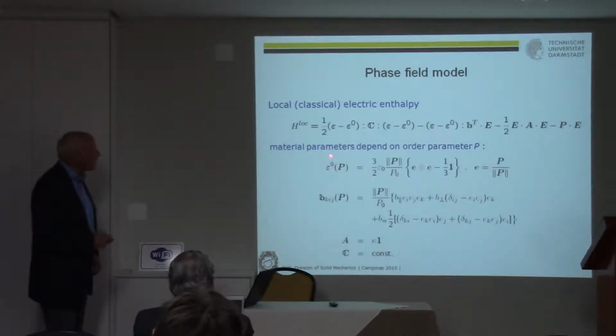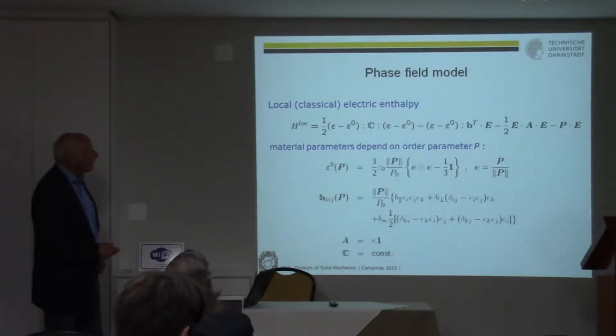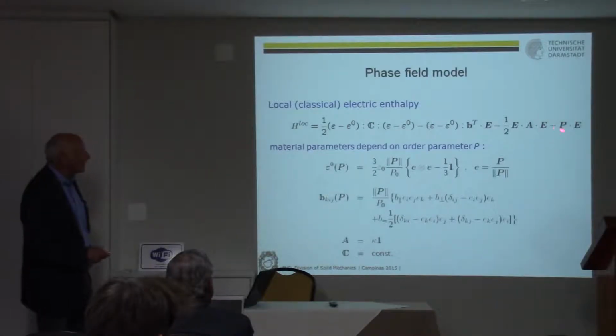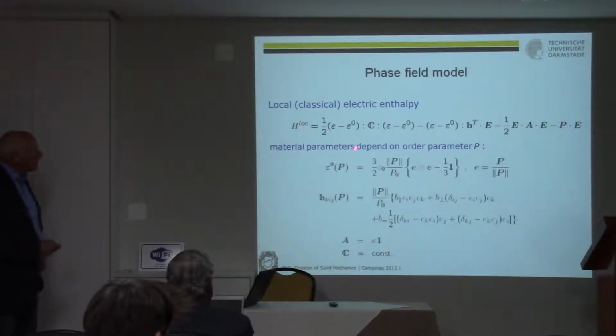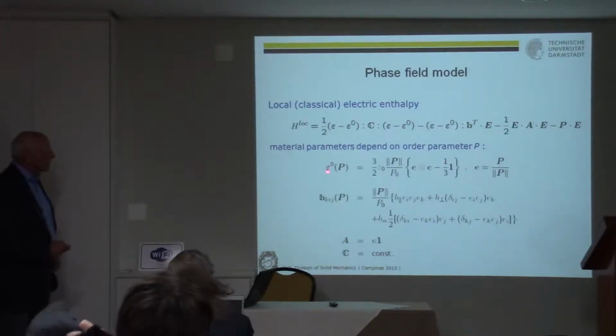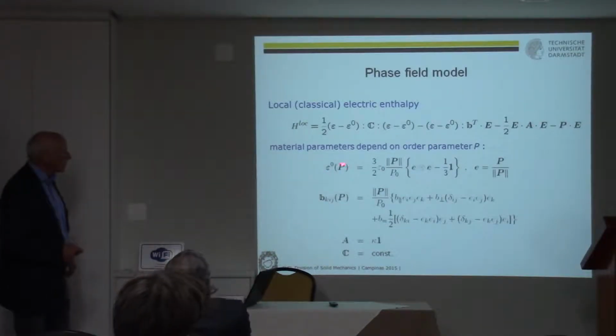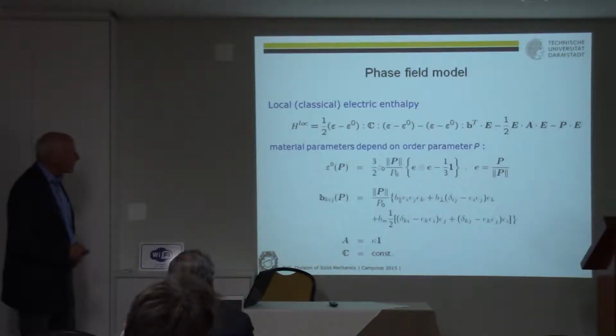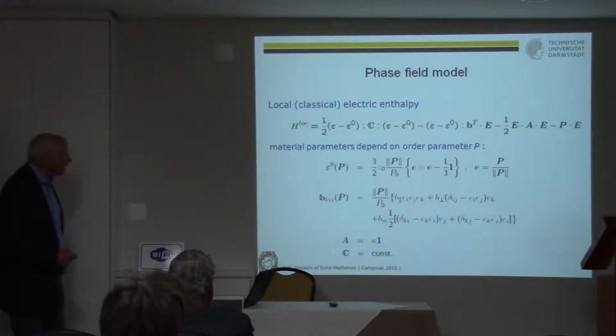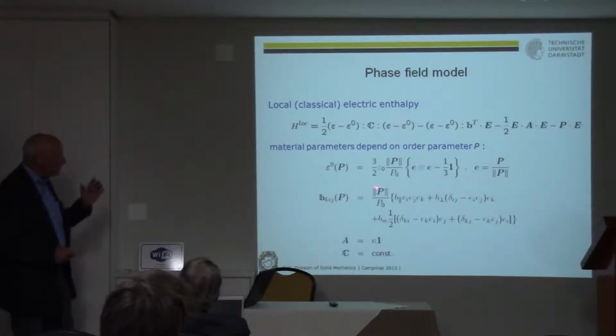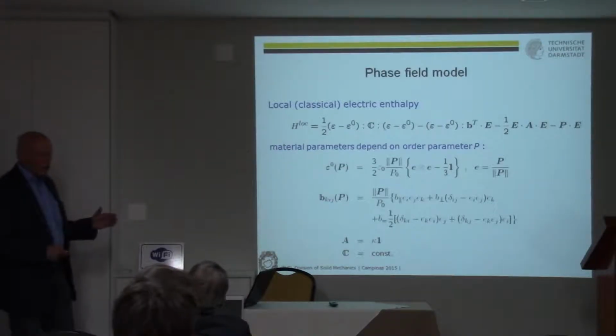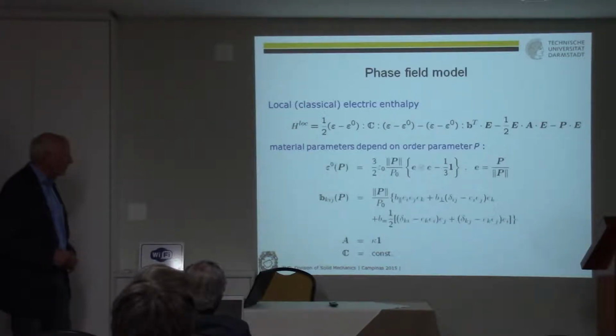Okay. Now the electric enthalpy consists of several parts. The first part is the pure mechanical part here, and then the pure electrical part here, and then the coupling, and then one term for the polarization, and epsilon naught here. This is given by the initial polarization P, as I mentioned, and here this tensor, b_kij, depends on the polarization. This means that the material constants depend on the polarization itself.